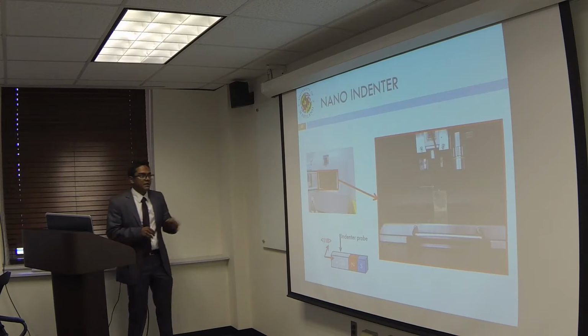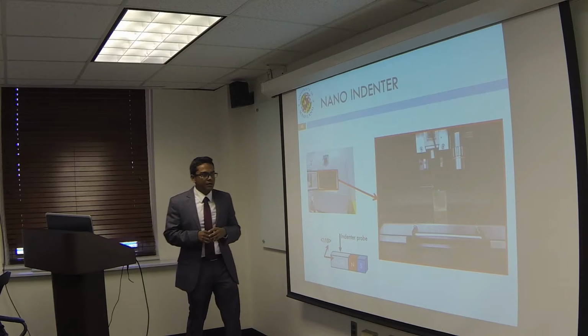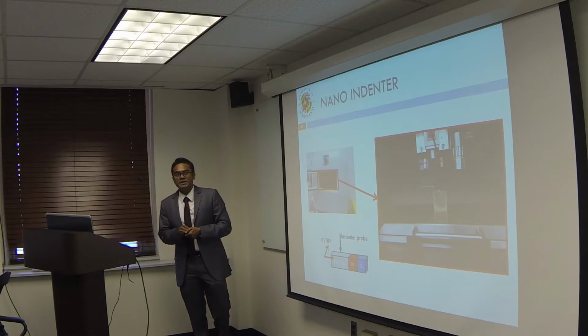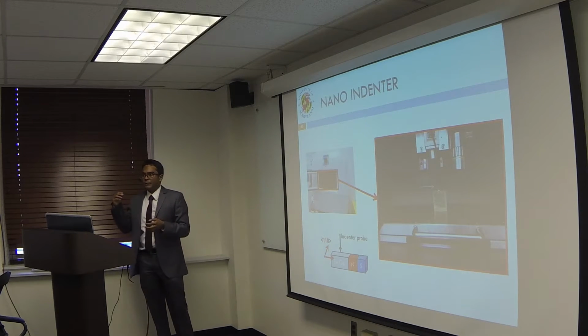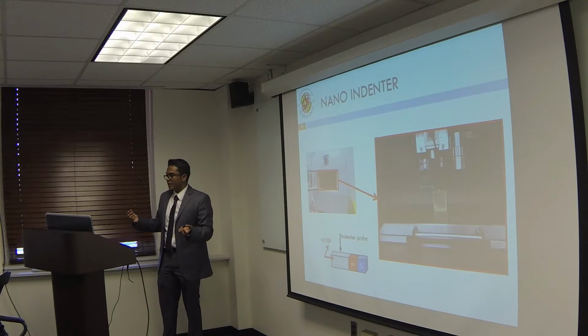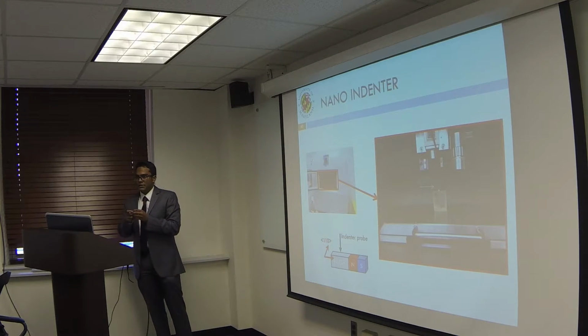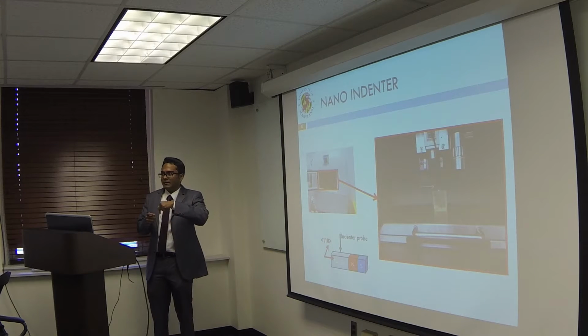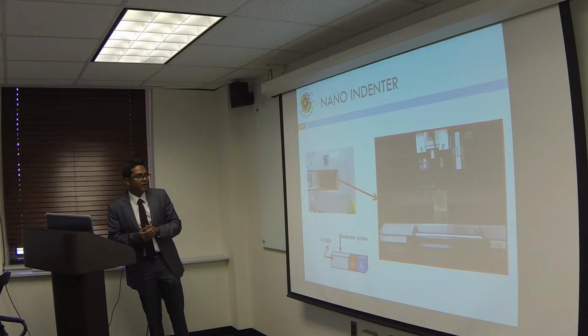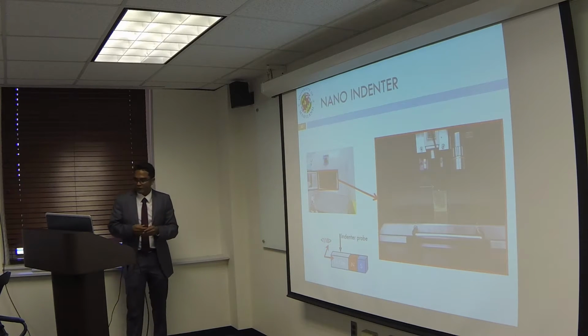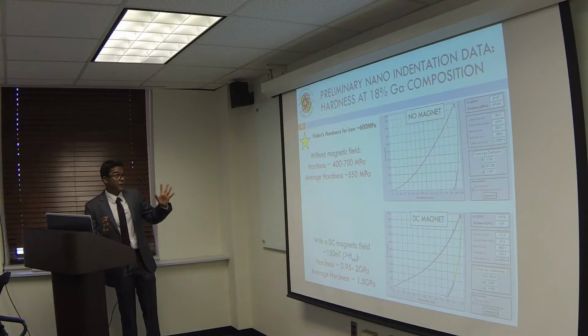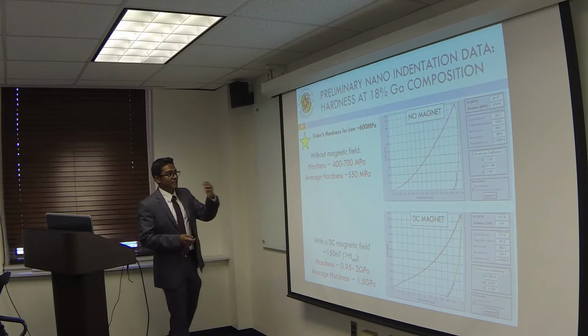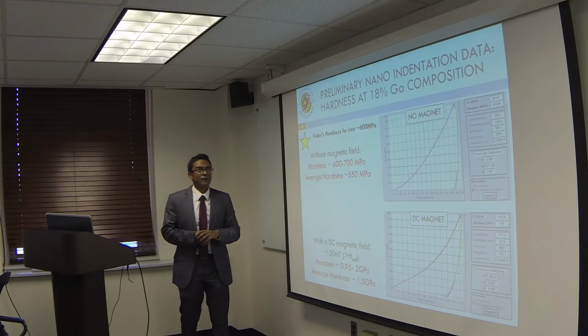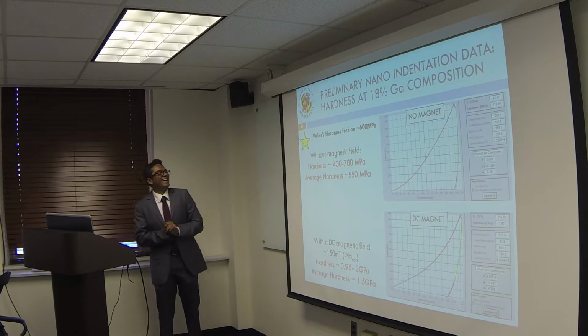So we decided to stick our samples into a nano indenter, and we did some Vickers hardness testing. So we tested the sample with and without a magnetic field. So we put a permanent magnet right next to the sample, and we indented it, and then we also tested it without the presence of a magnetic field. And the results that we got were very, very exciting. I actually got these results just last week, well, 2 days back, actually.